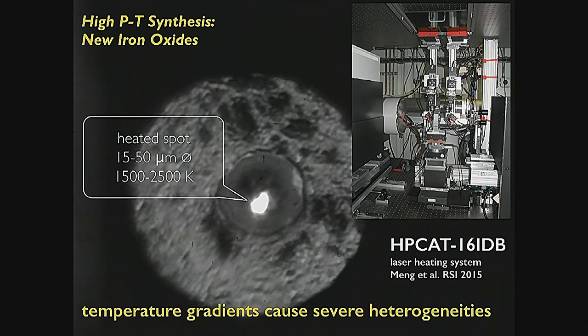But I wanted to do something more, especially with synthesis, something more dynamic. So to me, synthesis in the diamond anvil cell was a way to go. This is a picture of the HPCAT 16-ID-B station. The diamond anvil cell is that small thing at the center in there. You have all this other equipment around. High pressure beam lines tend to be really busy. And there's a whole optical table on top of it that allows you to deliver two lasers on the two sides of the diamond anvil cell and collect the image of the sample, the glow of the sample being heated, while you collect X-ray data at the same time.